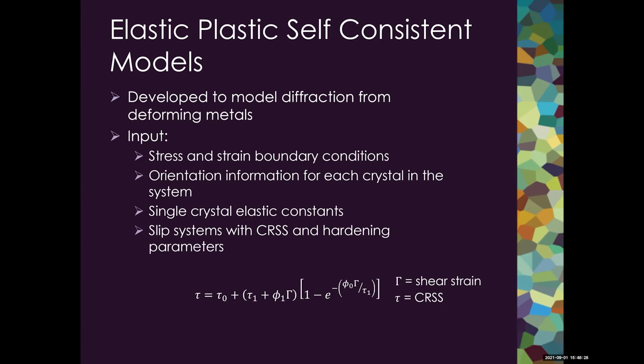So this EPSC forward modeling technique was developed by Carlos Tomé and Bjørn Clausen, among others, interpreting neutron diffraction data. And what they do is forward model the material and then adjust the slip system parameters to match their observations. And so the input for this model includes the boundary conditions, whether it's stress or strain, a list of grains in the material and their orientations, single crystal elastic constants for the material, and the active slip systems with the critical resolved shear stress and the hardening parameters.